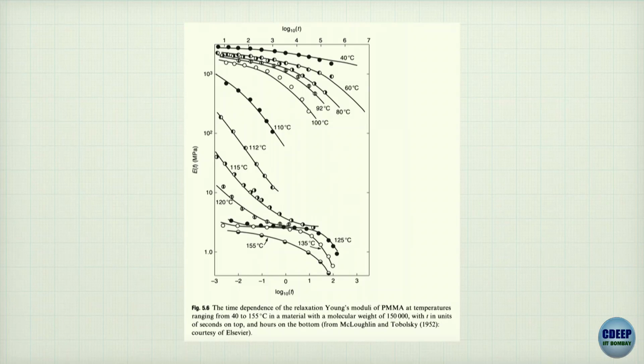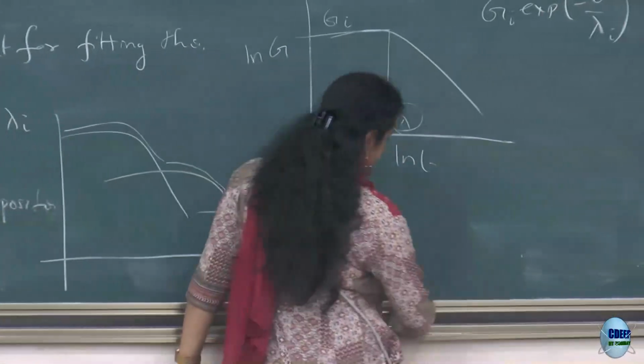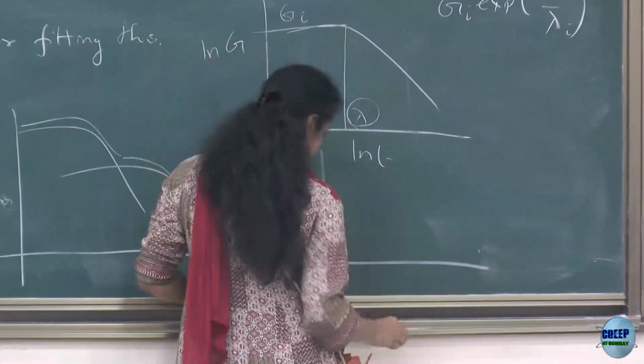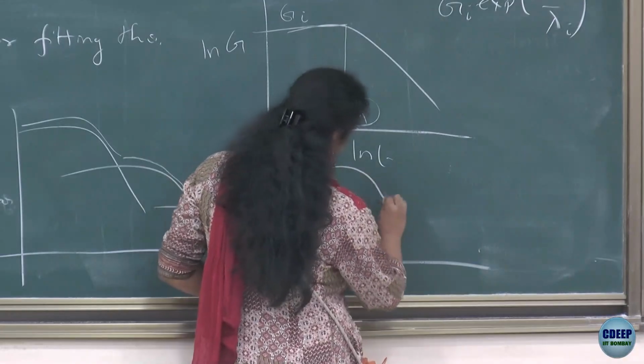Now, what has been shown, and we will discuss it, is that there is some level of similarity in all of these graphs. So, if you see the data at 110 has some similarity with the data at 100, that has some similarity with the data at 112. It kind of looks like they are shifted. And what has been shown is that you could actually superimpose all of these graphs and create a master curve which represents all this data on a single plot, indicating that different times could be modeled as data at different temperatures. So, in fact, all of that data gets superimposed on a plot of this type.